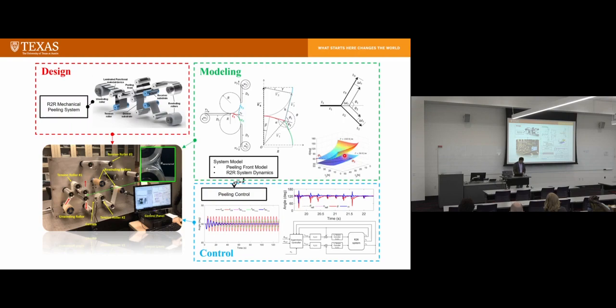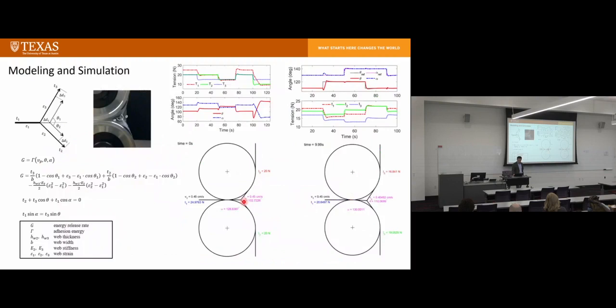That presents a very high challenge to control systems. So we develop a system model, and then we develop a peeling control framework, and then we can control our process. So a little bit of modeling and simulation. So basically, we use energy balance. We have this energy release rate and adhesive energy. And then we have an energy balance and force balance equation. Then we develop a simulation model. This will run.